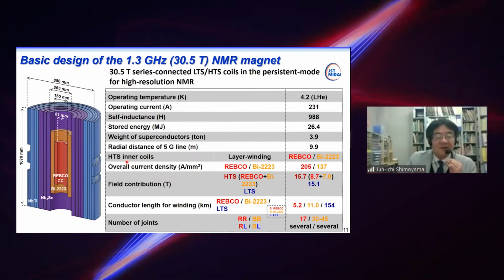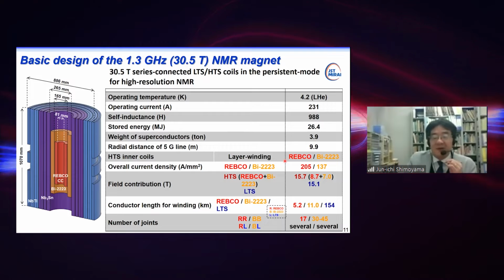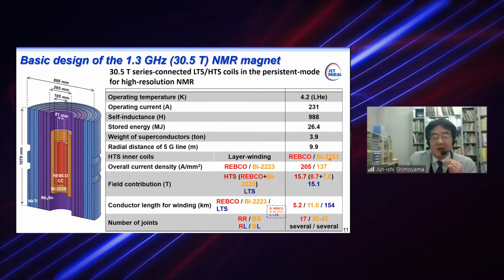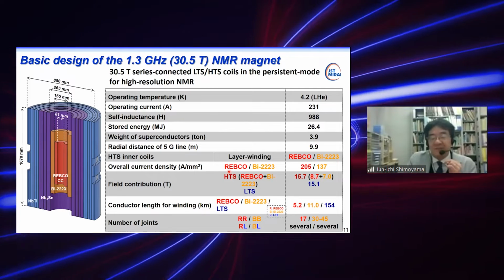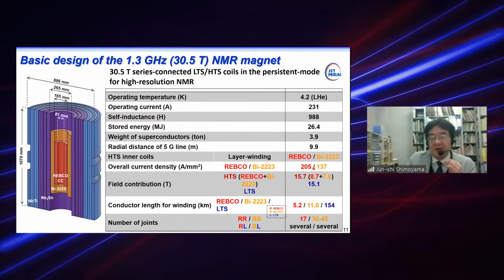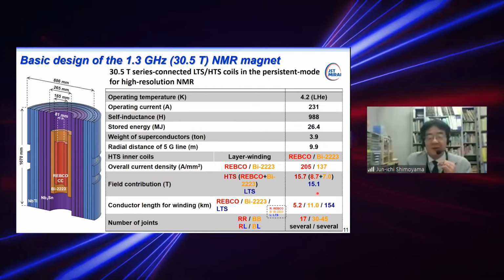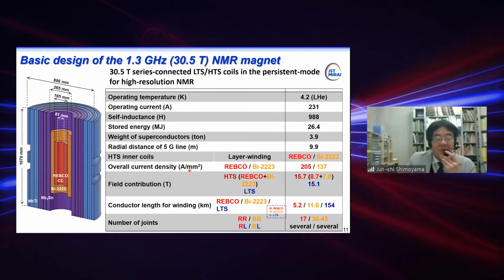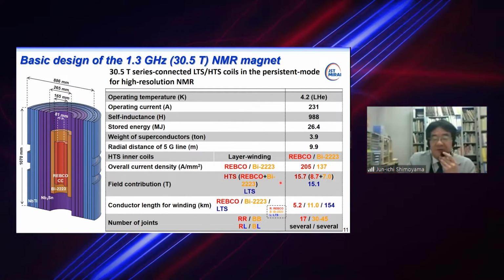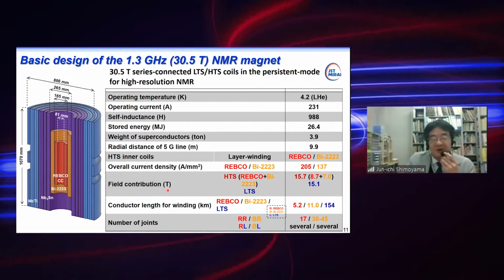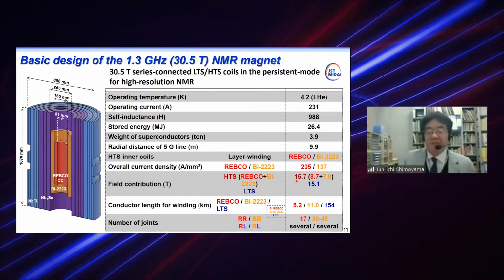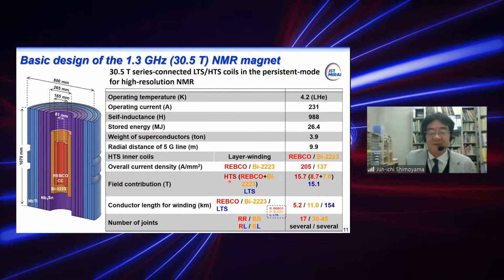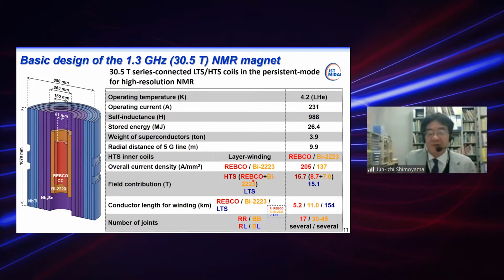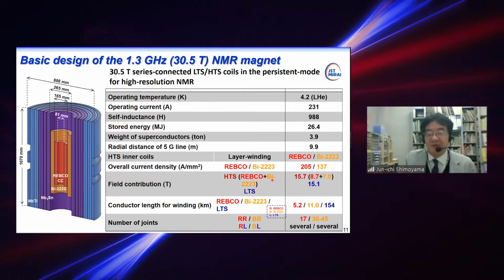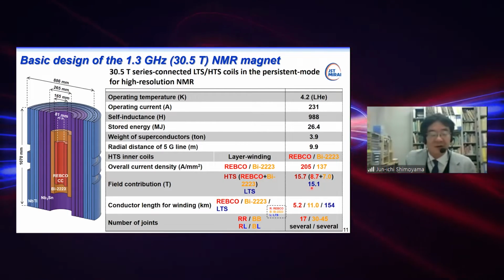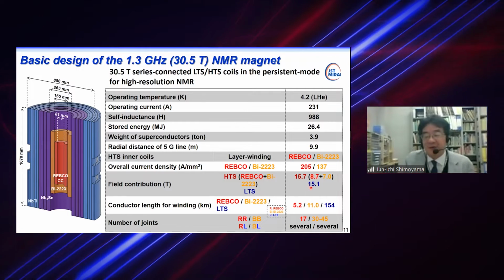The HTS coils are layer wound with REBCO and Bi-2223. The current density for those HTS materials is 205 amps for REBCO and 137 amps for Bi-2223, per square millimeter. Then, if you see this graph, you can find the field contribution of HTS is very large. In total, 15.7 Tesla will be generated by the HTS, REBCO and Bi-2223. REBCO generates 8.7 Tesla, and Bi-2223 generates 7 Tesla, while the low-Tc superconducting coils generate 15.1 Tesla.